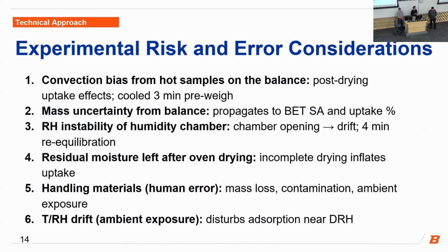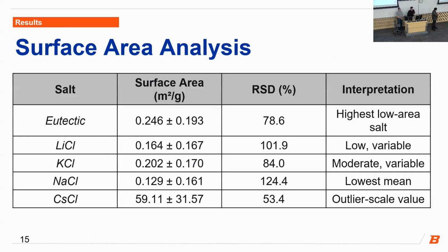And then to finish our technical approach, we wanted to do an experimental risk and error consideration section, and we came up with 6 main points. The first is convection bias from hot samples on the balance. The second is mass uncertainty from the balance. The third is relative humidity instability of the humidity chamber. The fourth is residual moisture left after oven drying. The fifth is handling materials or human error. And the sixth is temperature and relative humidity drift due to ambient exposure.